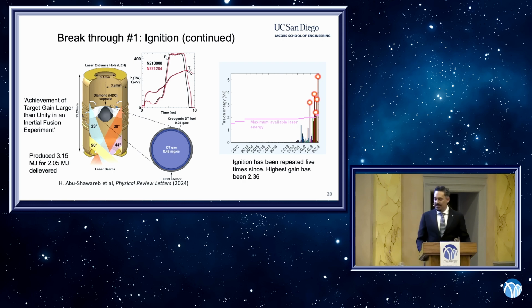So ignition has been repeated 5 times since, and the original experiment showed a gain of about 1.5, so 1.5 times more energy came out than was put in, and now the highest gain is about 2.36 at the hohlraum level. Actually, at the target level, it's more than 10. So you're getting gain of more than 10 inside this target. Okay, so very exciting, and that's giving people a lot of interest there.